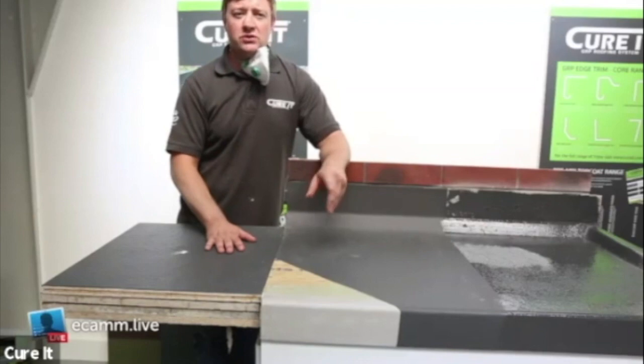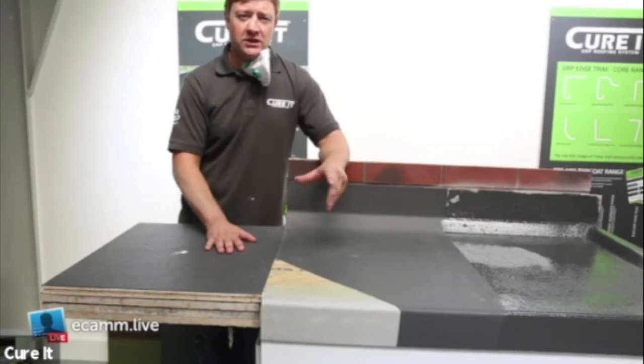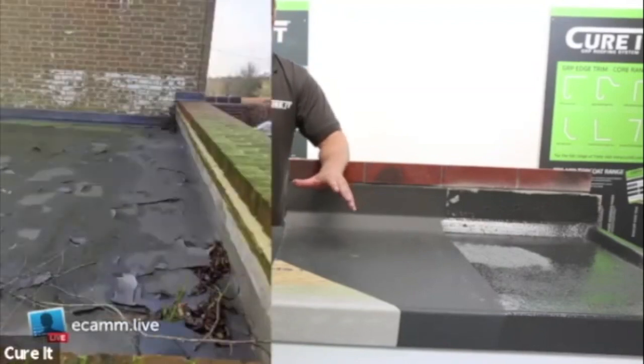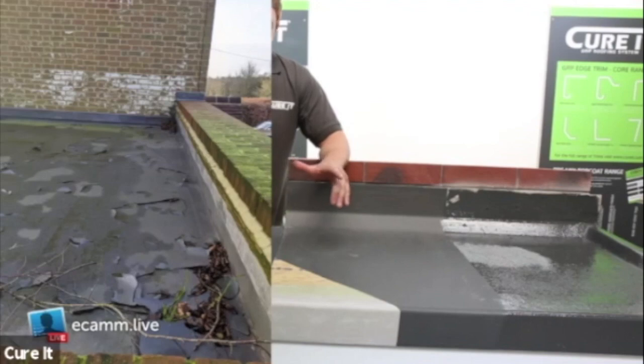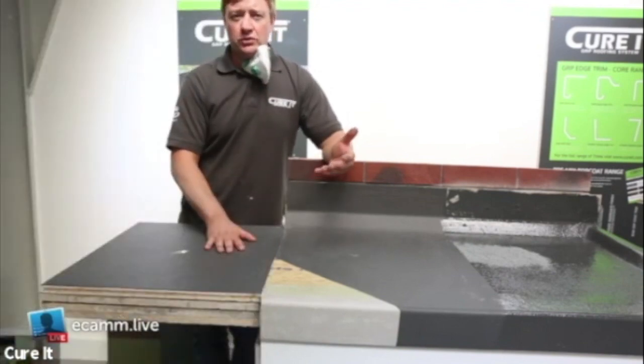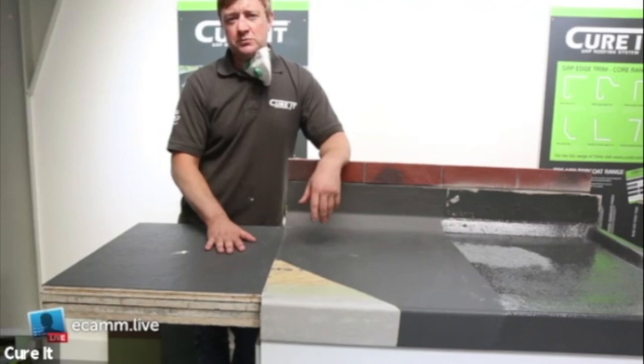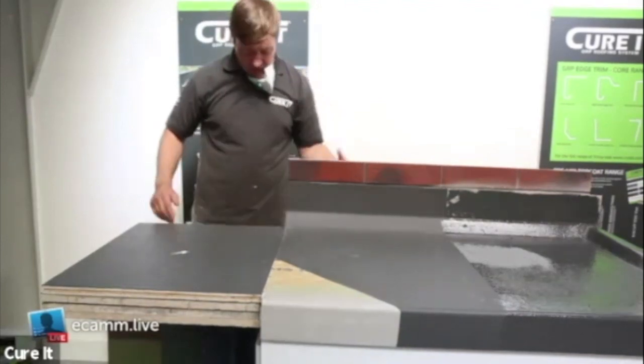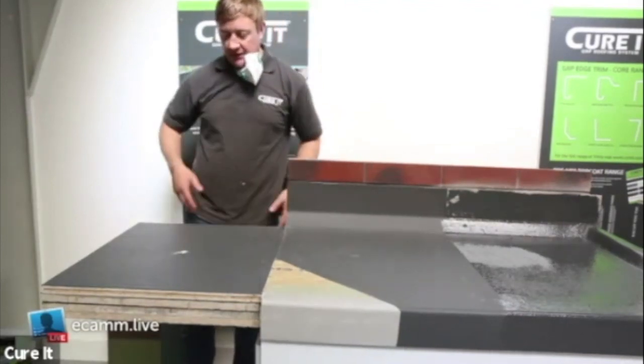Now I have got a little picture here as well to show you so you can visually see what we're talking about. And you can see on here the flaky top coat. Now it has been applied a little bit thick as well, but you can also see the grey under the actual grey as well. So when you're applying top coat on top of top coat, it's just going to peel off and you're going to end up with that delamination and it just spoils the appearance of the roof. It won't necessarily cause the roof to fail, but it will obviously spoil the appearance as well. No doubt the customer will be ringing you over that.